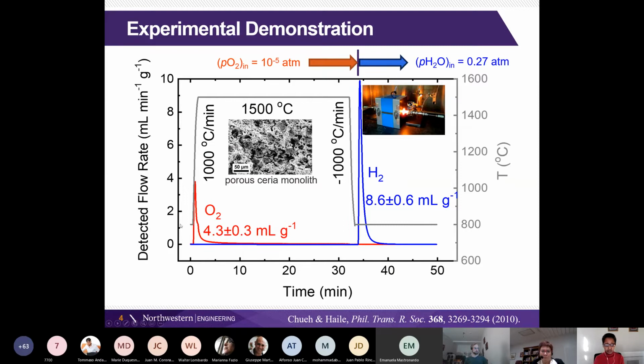Okay. And so we've done lots of experimental demonstrations of this. Others have as well. So here's the oxygen release when we heat the material up under this inert atmosphere. We get exactly the amount of oxygen we expected. And then after we cool it down and introduce steam, we get exactly the amount of hydrogen we expected. And we've cycled this hundreds of times, and it's very stable. And you can see that we use a porous ceria monolith here with relatively short diffusion lengths of a few microns and a relatively open porosity. We can't go to nanoscale features because that would, of course, coarsen away at high temperature.